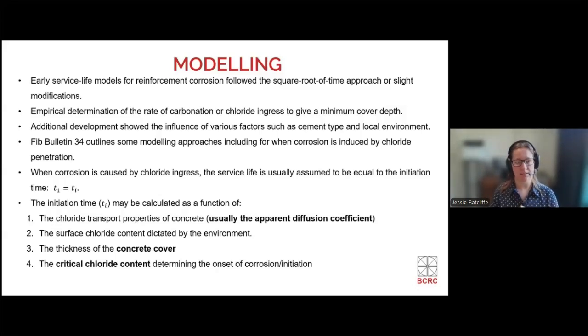We don't really consider the propagation, so the actual corrosion and spalling carrying on, because that can be relatively short in duration compared to the life leading up to that point. And there's a lot of uncertainty around the consequences of localized corrosion. So exactly where that spall occurs could make it critical or a non-issue. So we don't consider that section.